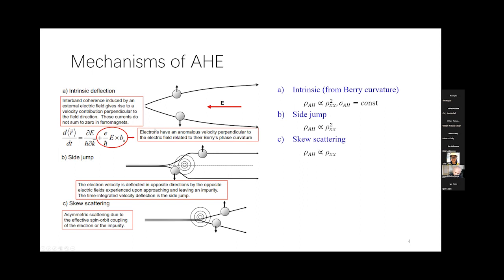One is intrinsic, in which the electrons have an anomalous velocity perpendicular to the electric field, which is due to their Berry curvature field. And because the anomalous velocity is independent of the electron's lifetime, you have an anomalous Hall conductivity equal to a constant. The other 2 mechanisms are extrinsic, including side jump and skew scattering.